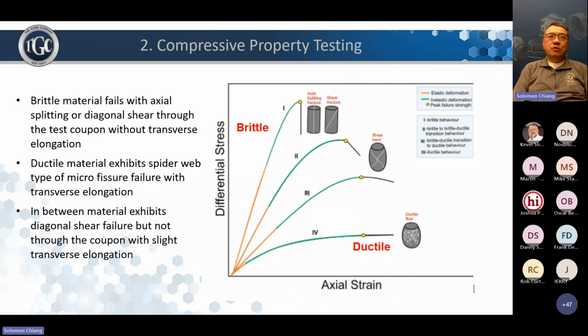And also, if it's a brittle material, when it fails, it's an axial crack right down the middle or diagonally. That shows a brittle material failure. A ductile material, if you compress it, actually expands a little bit and looks like a barrel. And there's a Poisson ratio that talks about the displacement in the y direction to the compression in the x dimension, but we won't cover that in this webinar. But that is a very important number for the finite analysis also. The failure mode is not a vertical crack or diagonal crack. It's a lot of minute failure. So just by looking at the coupon after it failed, you can tell whether it's ductile or brittle material.